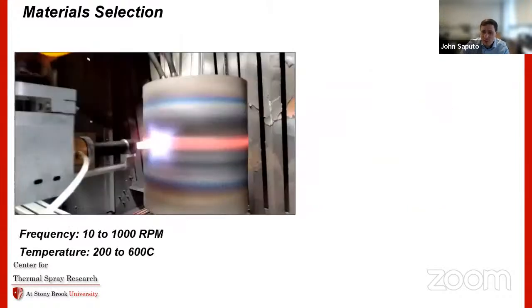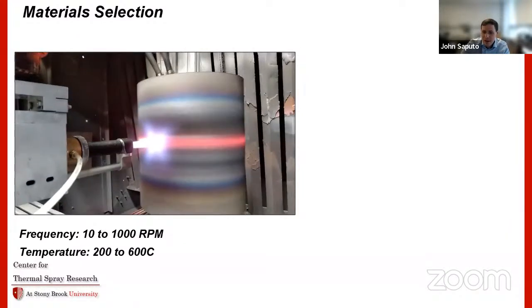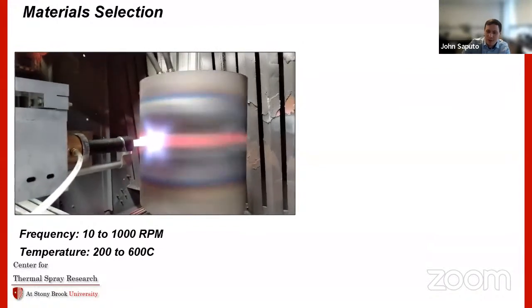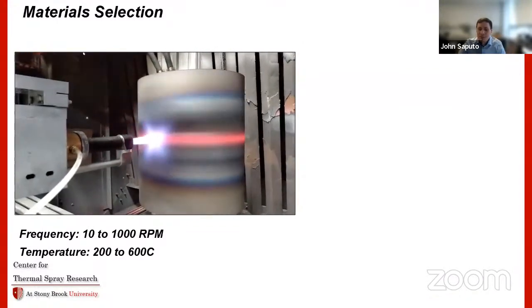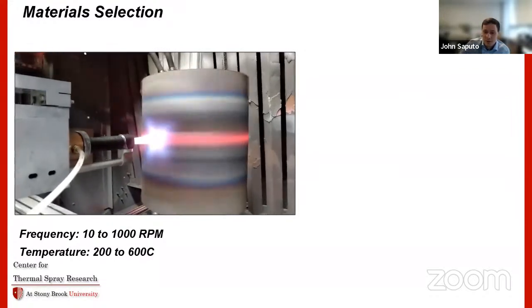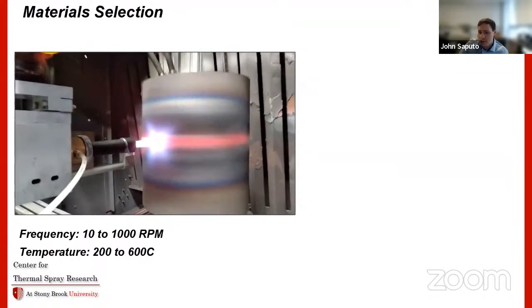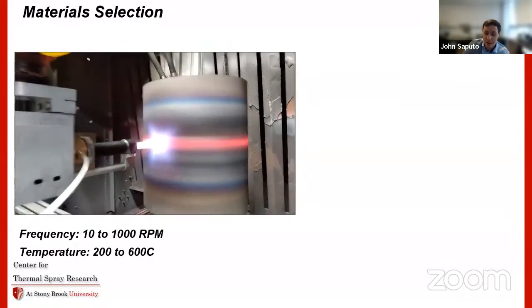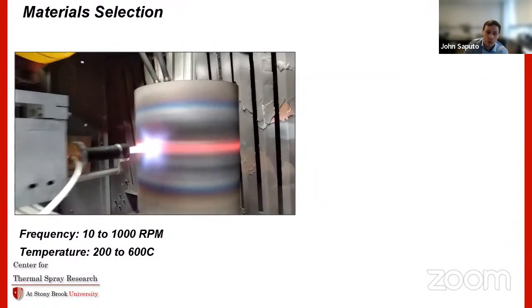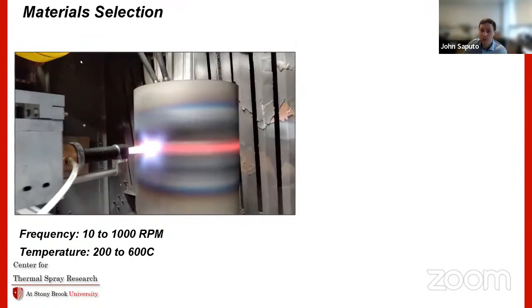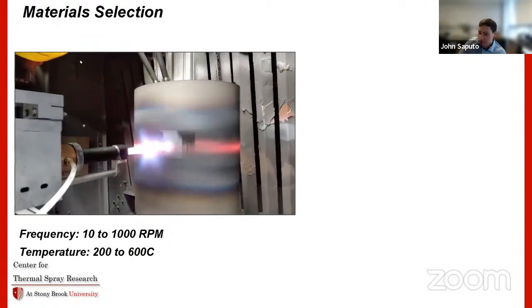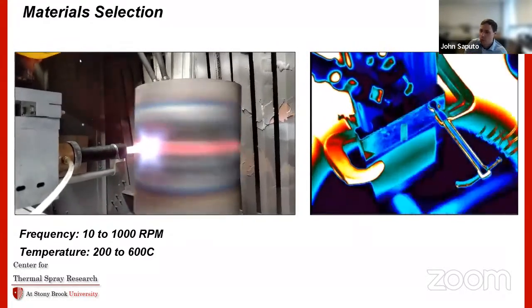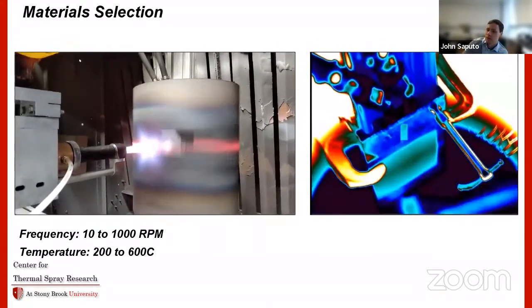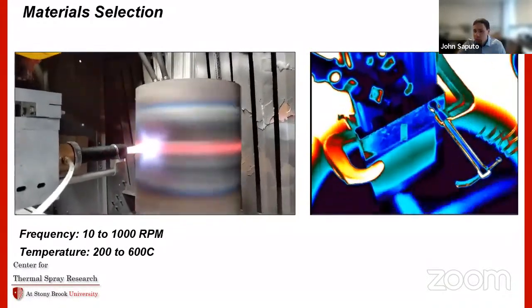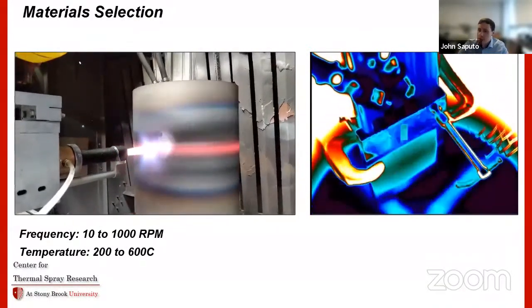So we're just using an HVOF torch and this sort of spinning shutter. It's a steel cylinder with a hole in the center. And it sort of rips around the coated sample in the center and gets rapidly shocked by this HVOF torch. So we're able to do this at frequencies between 10 and 1,000 RPMs and push the temperatures between 200 and 600 C, really making it relevant to the conditions that you might see in an engine. So we can do this test and record the surface temperature transients using a thermal imaging camera to really understand what's happening to these coatings in these systems.